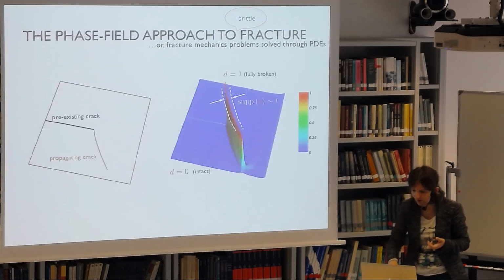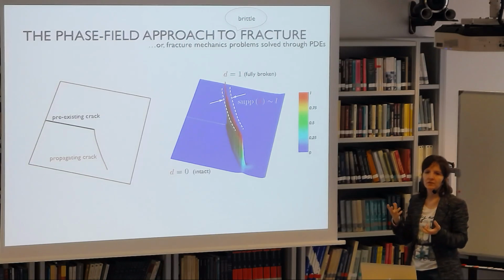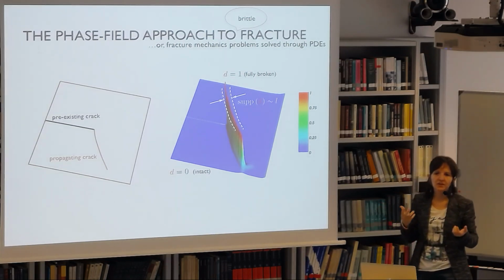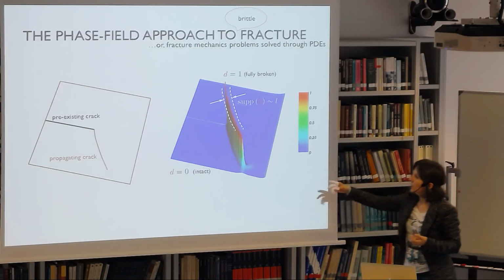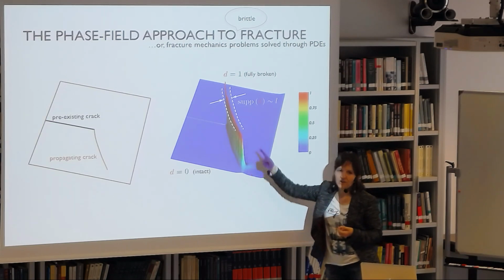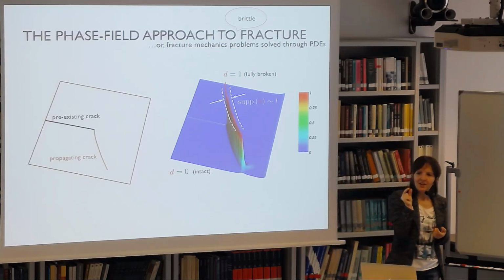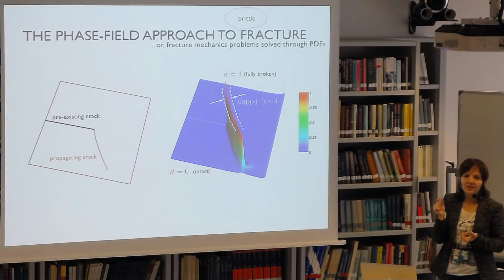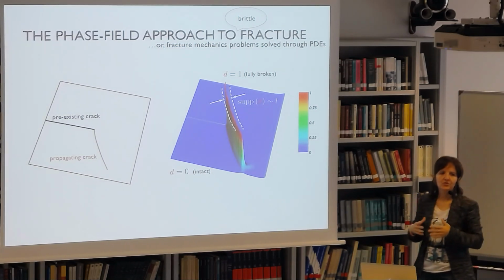Of course, you can also understand within numerical methods, such as the finite element method, if you want to resolve such a steep variation, you need fine elements. So the elements must be fine enough to resolve this variation. So the smaller L, the finer the mesh that you need to use.